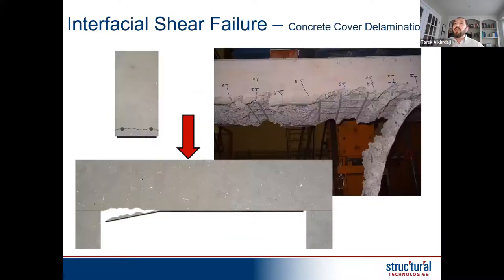And that limit is basically a design limit that we account for in the design. Here you can see this is one of these failure points. The nice thing about this photo, although it's showing failure, is that we ripped the concrete off the beam. So the failure is not really as someone would imagine it. It's really at the surface of the bond of the FRP.